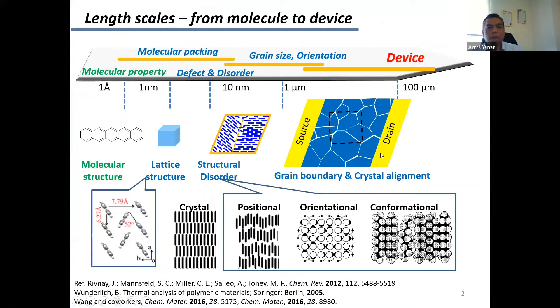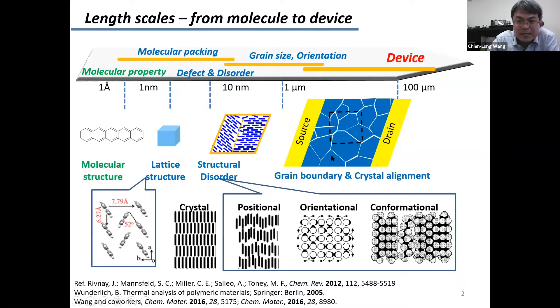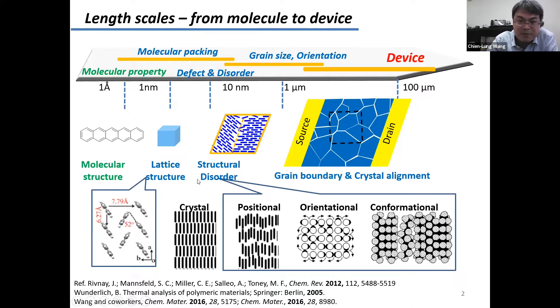So let's start from OFET. Here is the top view of an OFET device. The conjugate molecules are responsible for transporting charges from the source electrode to the drain electrode. In order to get high mobility, the conjugate molecules should have a suitable chemical structure and need to pack into a lattice that gives very nice high pi-pi stacking. Above that, these molecules should form a thin film that has a low density of packing defects.